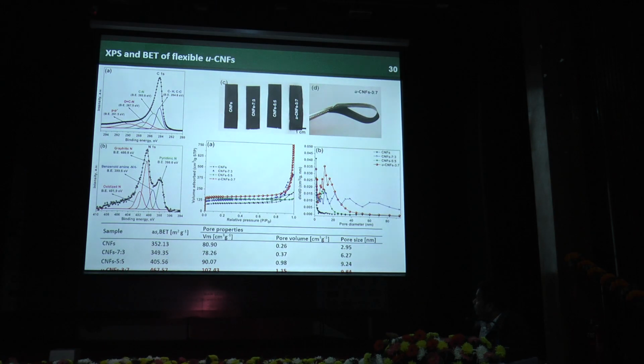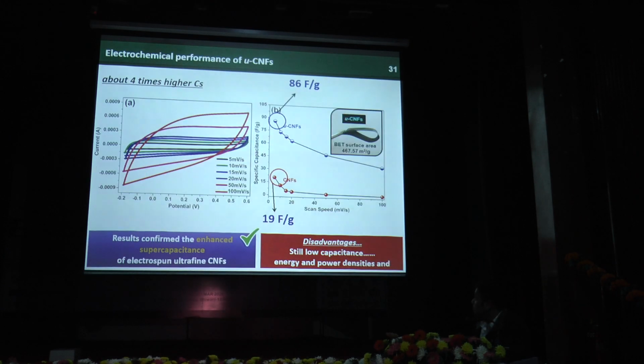So this result shows how the surface area is changing. With the carbon fiber, the surface area is close to 350, and the multi-channel carbon fiber is around 467. So the modification and the channel structures are very important to bring the surface area and also porosity. So we did some preliminary testing to test whether the material can be suitable for the energy storage application. And when you compare with the commercial carbon, it shows very high energy storage capacity.